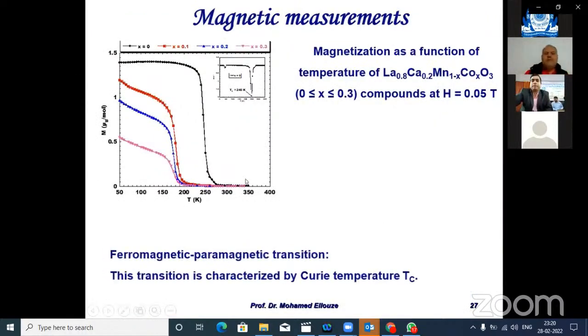Now I will talk about the magnetic measurement, which is very important in our study. Here we have magnetization as a function of temperature for this kind of sample with an applied magnetic field of about 0.05 Tesla. We can see that we have a paramagnetic to ferromagnetic state transition with decreasing temperature, and the reverse with increasing temperature.